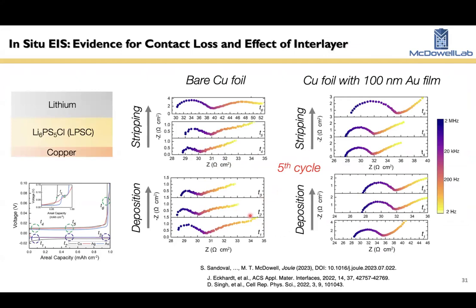and this is a busy slide. I apologize, but this is electrochemical impedance spectroscopy. It's pretty important. We did a lot of EIS measurements for this paper, and this is just a small portion of them. But what this shows is basically near the end of stripping, when you have bare copper, you get this distinctive spectral shape where you have this intermediate frequency region that grows, and we think this impedance spectrum feature is associated with void growth near the end of stripping. When you have gold films, you don't see this sort of feature, and in fact, the impedance spectra remain fairly similar with cycling, which is a mark that there's good contact at the interface.